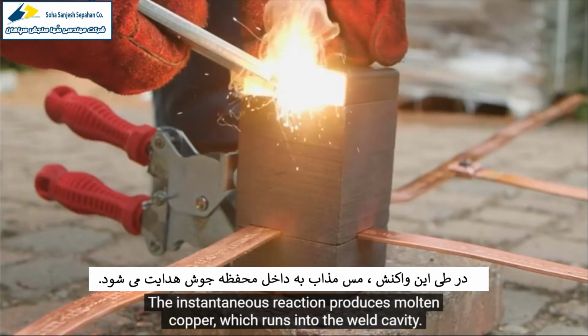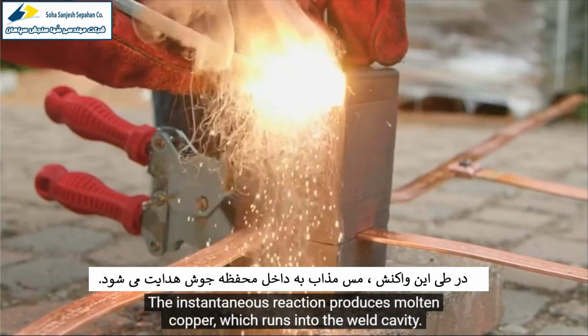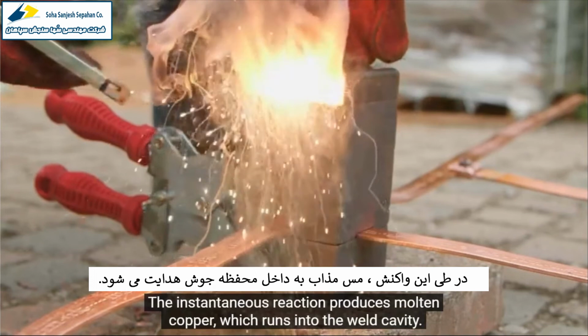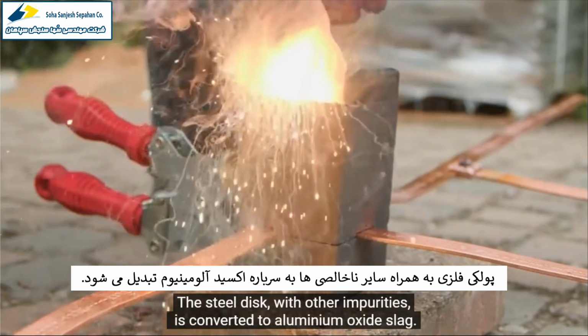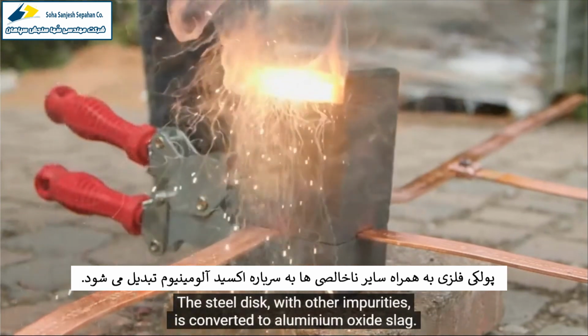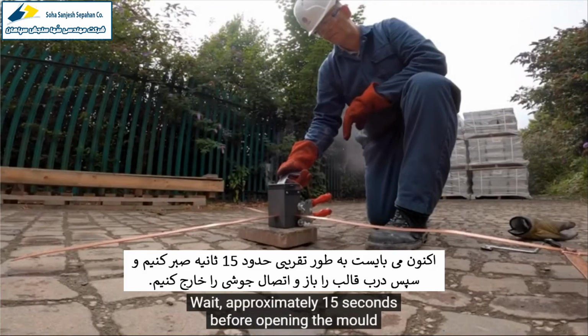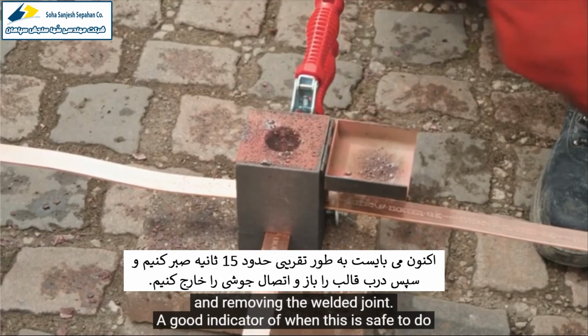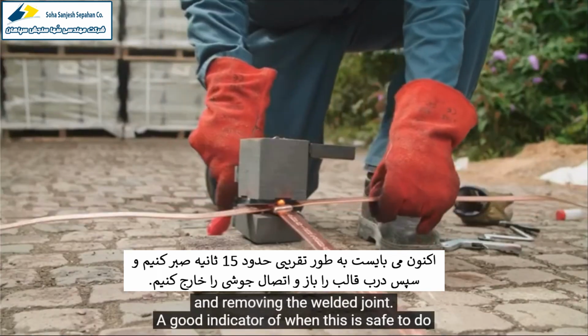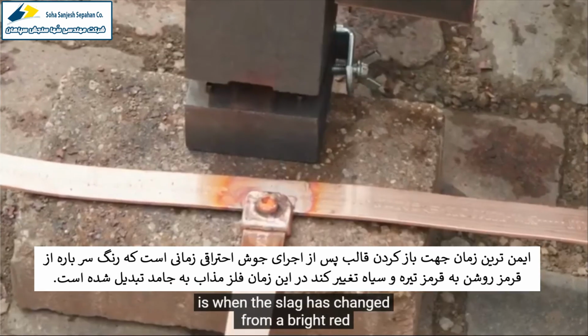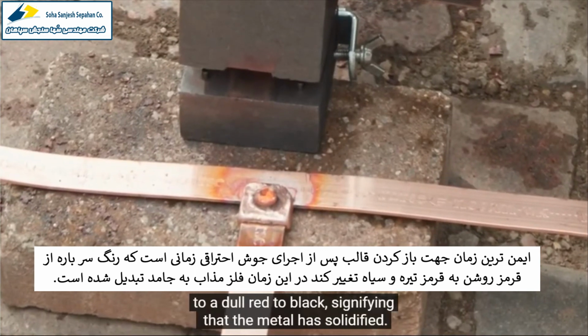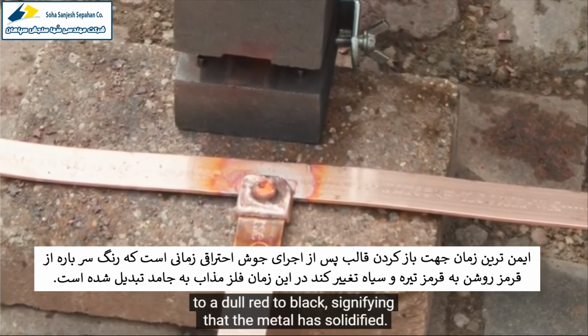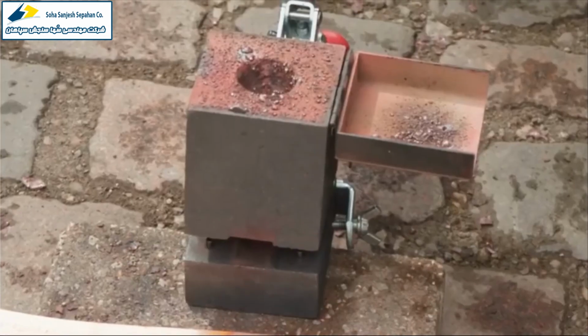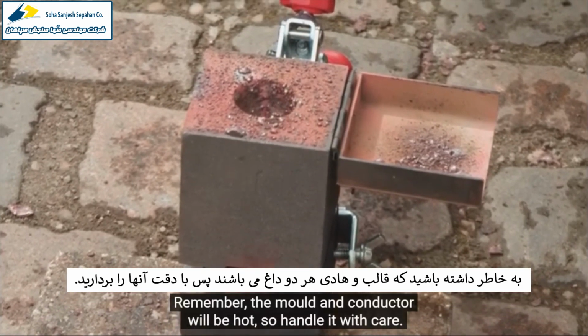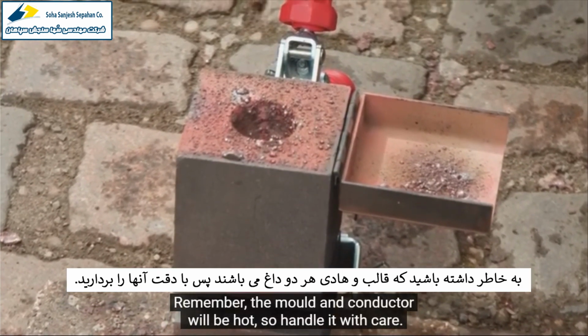The instantaneous reaction produces molten copper, which runs into the weld cavity. The steel disc with other impurities is converted to aluminium oxide slag. Wait approximately 15 seconds before opening the mould and removing the welded joint. A good indicator of when this is safe to do is when the slag has changed from a bright red to a dull red to black, signifying that the metal has solidified. Remember, the mould and conductor will be hot, so handle it with care.